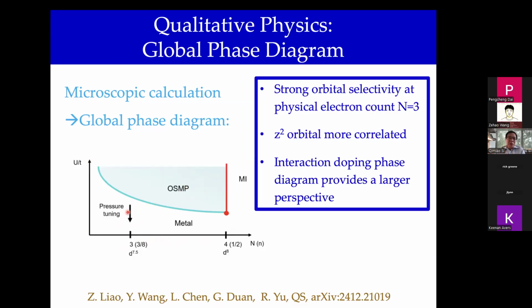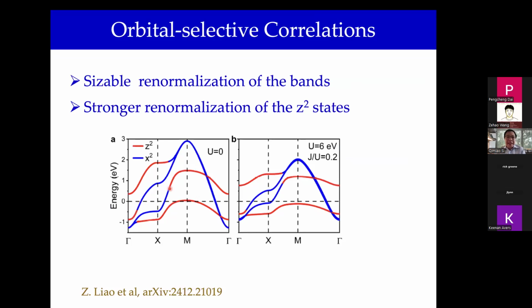So this is the overall perspective, and I want to get a sense of whether we're on the right track by comparing with the spectroscopic measurement results. So first, in a single particle spectrum in our calculation, we compare the electronic states, the energy dispersion in a non-interacting case in this relatively narrow energy window near the Fermi energy versus the result of the calculation in the presence of interactions. Two things are reasonably apparent. One is that you can see the overall reduction of the bandwidth.